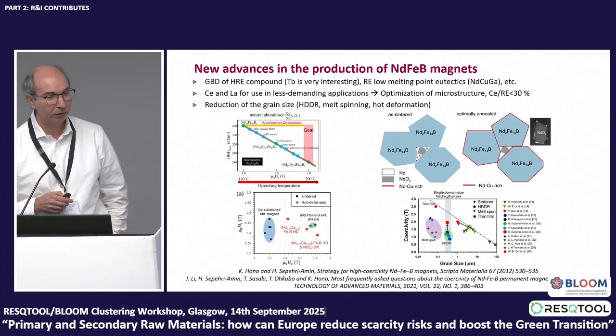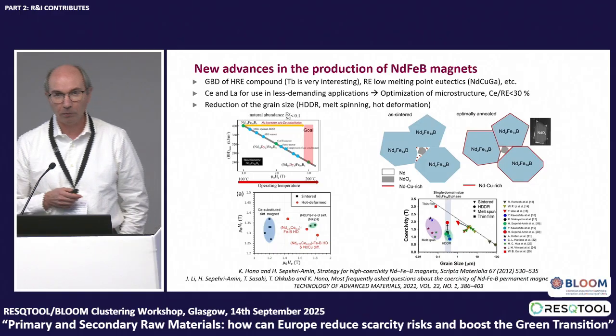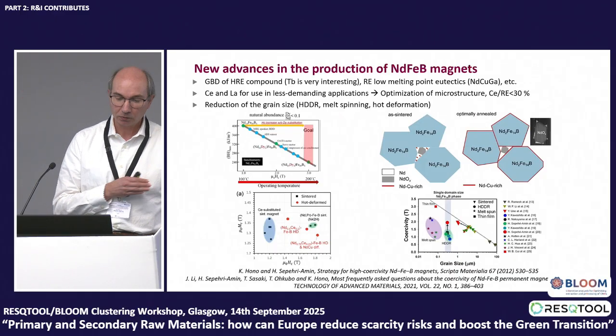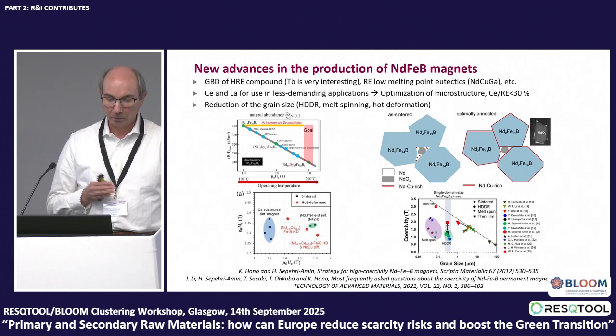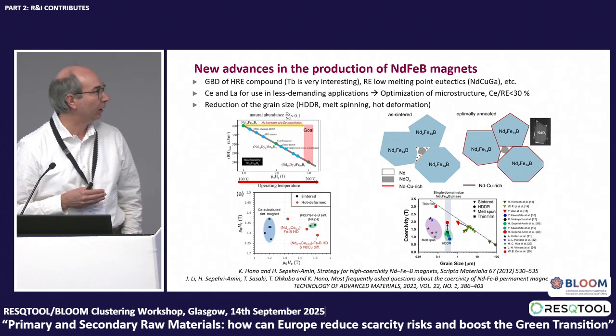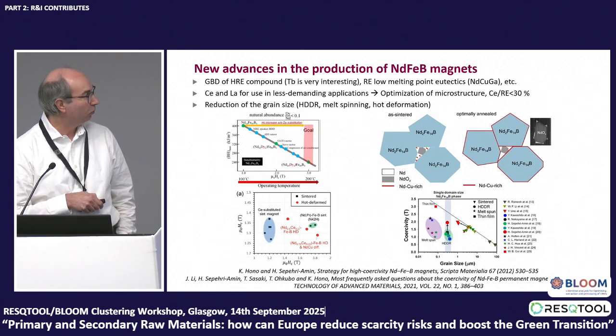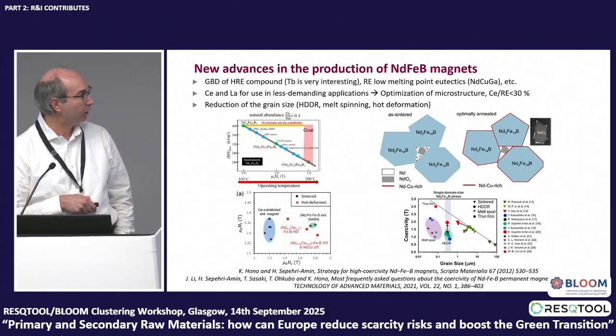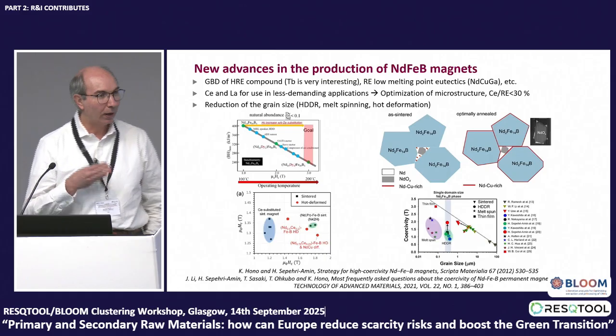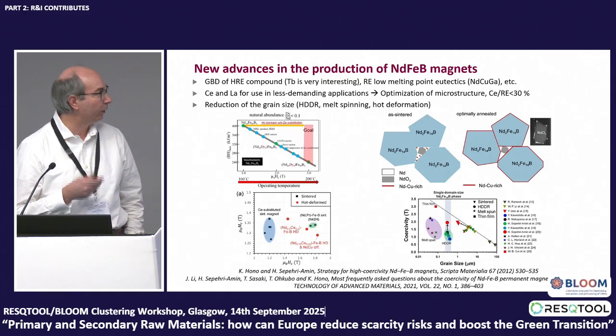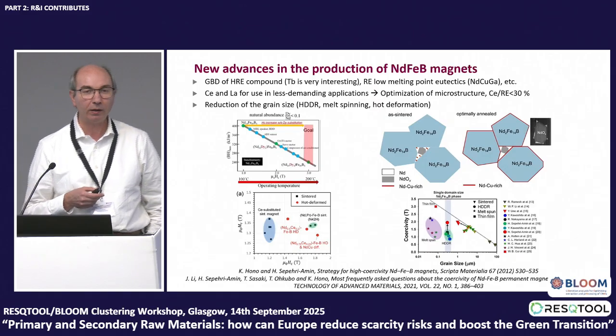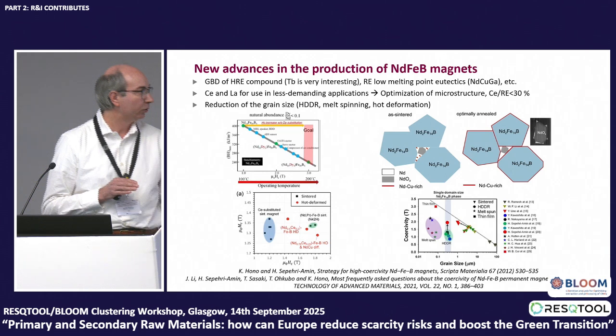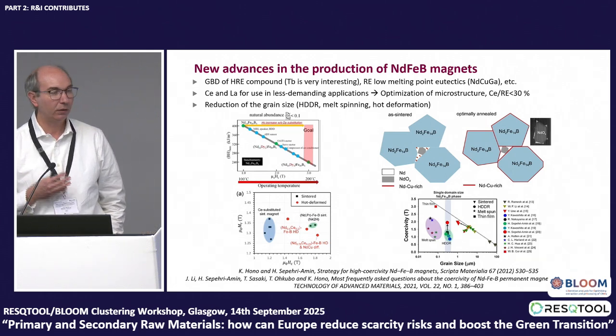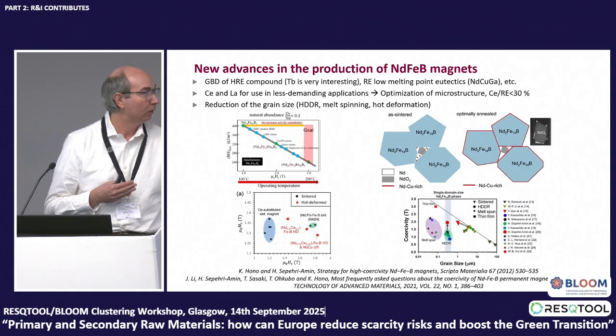So if we think about research and what the long-term trends are going to be, they are coming from the past as well. I would say that there are three interesting lines. The first one is the improvement, because basically what we want is to move this line horizontally to the right. That means increasing the coercivity without reducing the energy product of the material. And this will allow us to go to higher temperature applications without the need of spending more heavy rare earth elements, that is, keeping the cost of the magnets. So there are, I think, basically three ways that people are still actively investigating to achieve these targets.